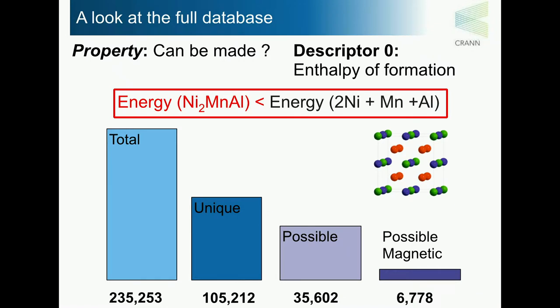Now, if you start from that, you start from a quarter of a million, and you find out that you have only 35,000 that passed this first criterion. So 90% of the thing you have calculated essentially goes away, right before you start. And our world has about 6,000 which are magnetic. Remember, we have about 4,000 magnets. So if I found new 6,000 new, that would be a fantastic deal. You will find out it's not quite as that.